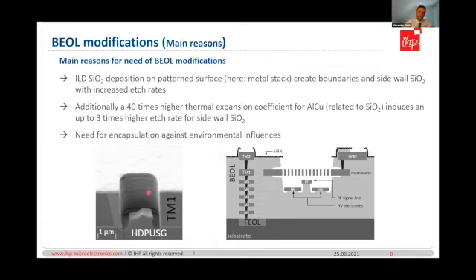To show this, I have integrated here an SEM image, which is prepared by FIB, the focused ion beam, in cross section, and you see here an interrupted wet etch process. You see that the sidewall oxide deposition is already etched, and the bottom is still remaining. This leads to parasitic etches, for example. Here is again the schematic in cross section, and these are the unwanted or parasitic etchings regarding the electrodes, regarding the membrane, and also regarding the pads. And what is also not shown here is the missing encapsulation.